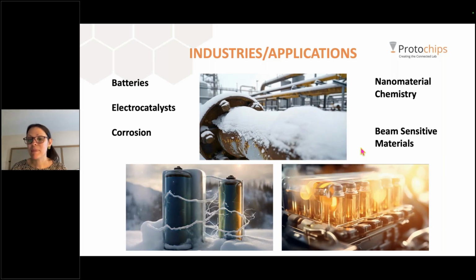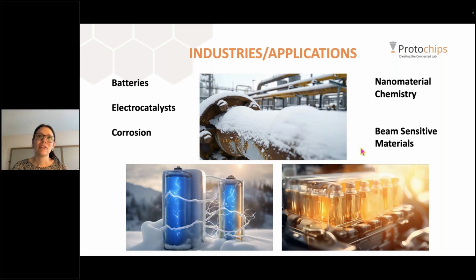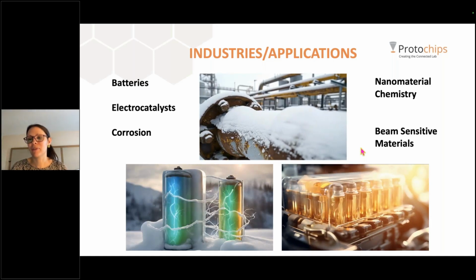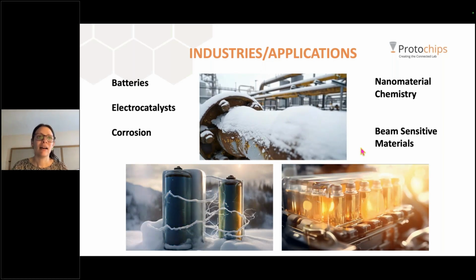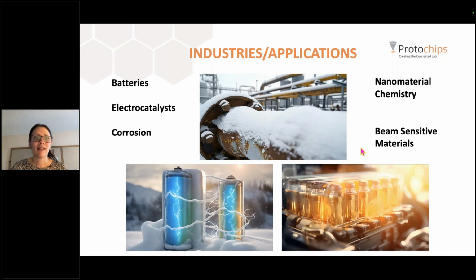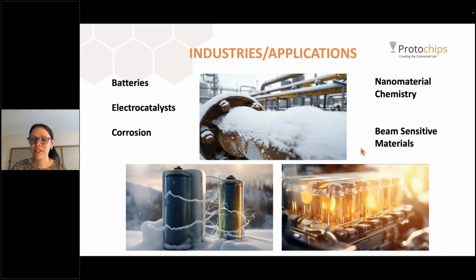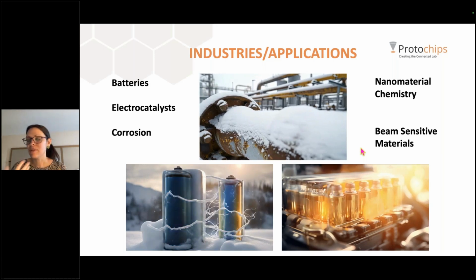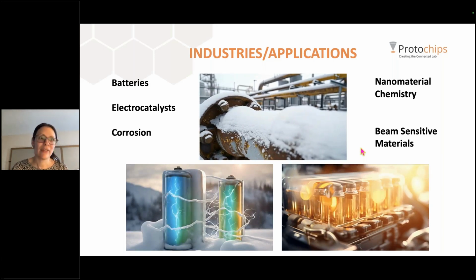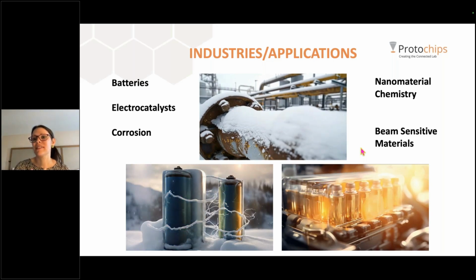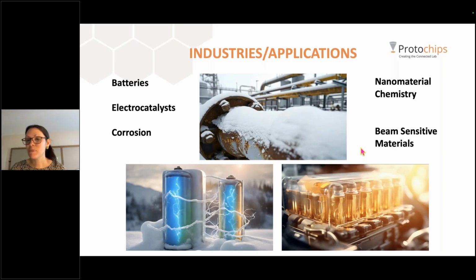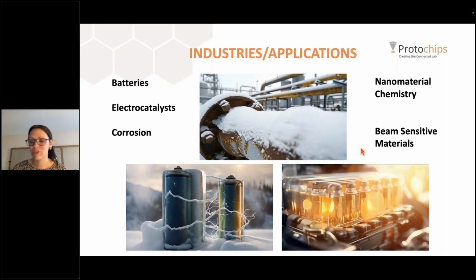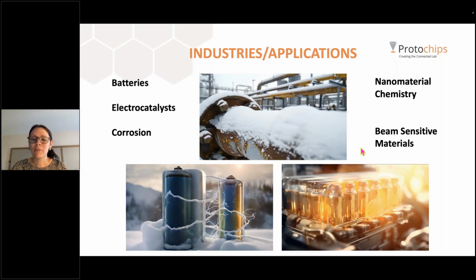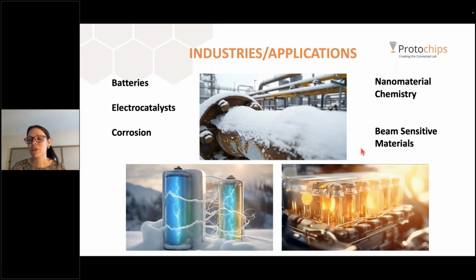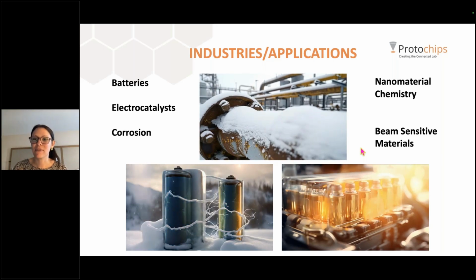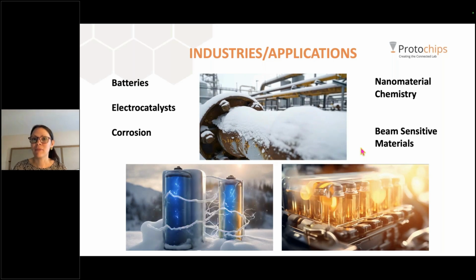Nanomaterial chemistry, another big area, because we've had a lot of feedback and requests. Researchers want to watch the nucleation and growth process of the nanomaterials that they're synthesizing. And a lot of them are synthesized in organic media. High entropy alloy materials, for instance, are synthesized between 200 and 300 degrees C in an organic medium. We had a lot of feedback looking for higher temperatures to watch this synthesis process of nanomaterials. And then, of course, beam sensitive materials across the board, whether you're doing electrochemistry or not, and you just want to image your beam sensitive material in a relevant liquid media, the cooling is going to help with that aspect and help you image these types of soft materials for longer periods of time.